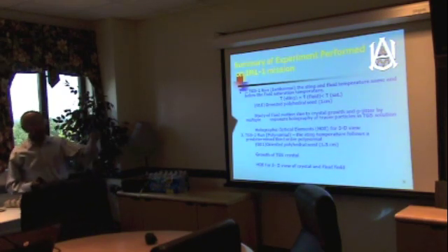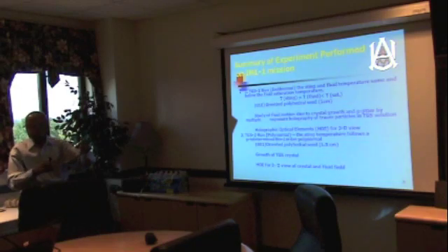We ran experiments with a cold finger, which I'll show you in a minute. The cold finger is a rod, and at the end of this tip the seed crystal was mounted to grow, and this seed was cooled by a thermoelectric cooler. The thermoelectric cooler was somewhere here, and that cooled the seed. So if I maintain the solution at a constant temperature and just cool this tip, the seed becomes cooler. That becomes the driving force. The solute tries to move towards the cool region and the crystal grows.